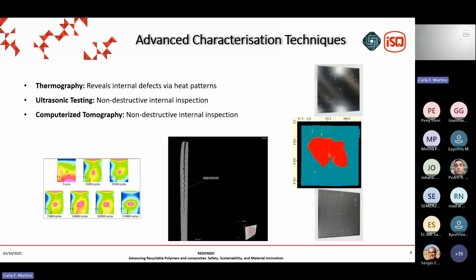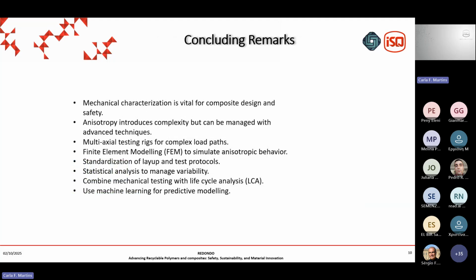The same goes for tomography, which is a very powerful tool to identify internal defects in our materials and localize them. The image here is a tomographic image of a section in the middle of one of these test panels, in which we can see a localized defect there in the middle. Specifically, this panel was to produce those specimens for mode 1, mode 2 testing for interlaminar resistance testing, in which it was difficult to identify the location of that initial defect, and tomography can allow this very, very well.